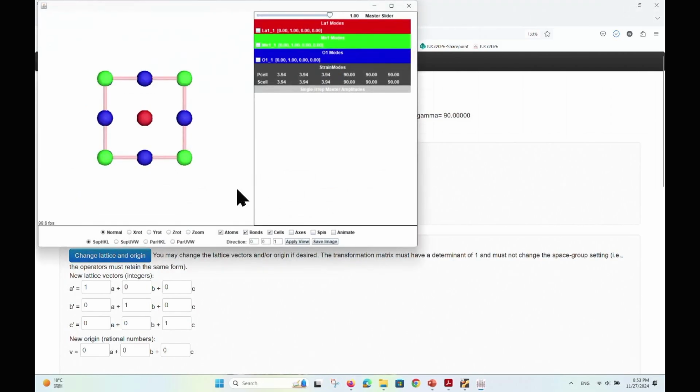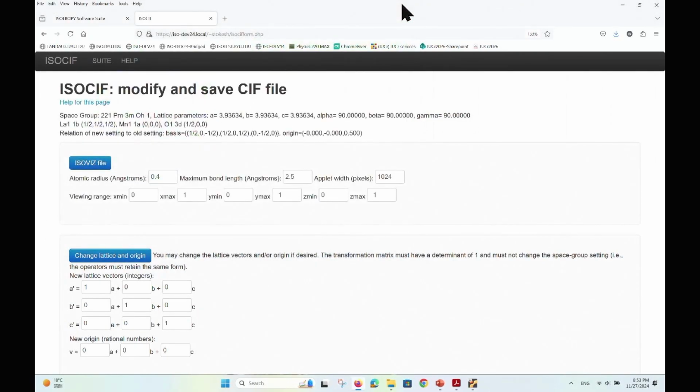Now I could have used space group 62 as the parent. That's no problem, and I could have compared the non-magnetic to the magnetic structure with the same displacements. But if I want to simultaneously explore the displacive distortion and the magnetic distortion, it's possible to eliminate all of these distortions, and I get a nice cubic parent, and I can export that. I can save that. So you download any structure from the Bilbao Crystallographic server, or take any structure from the literature, and then you can create a parent structure from it, and then do a comparison of parent versus child.